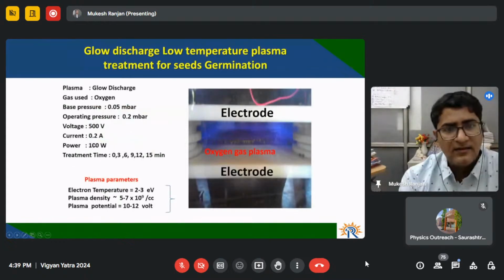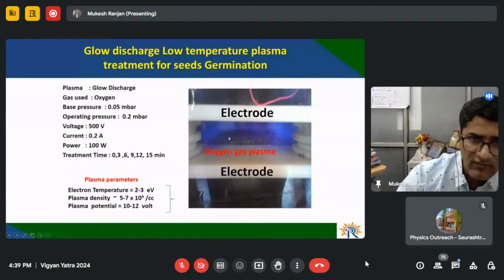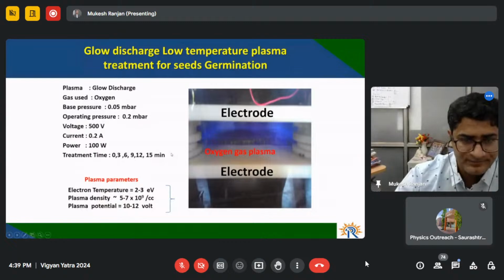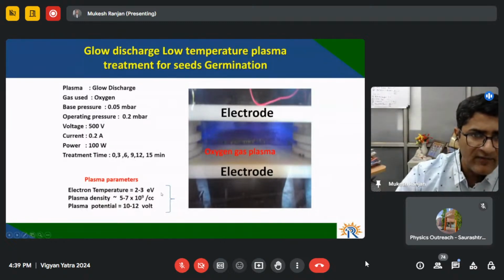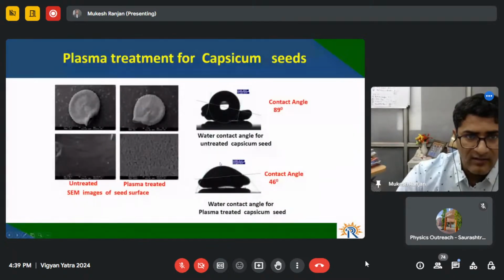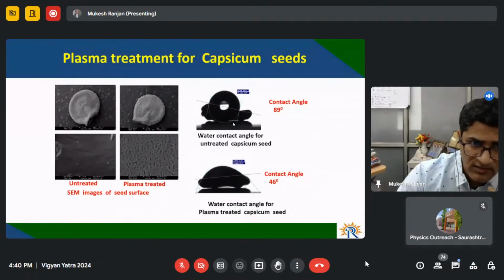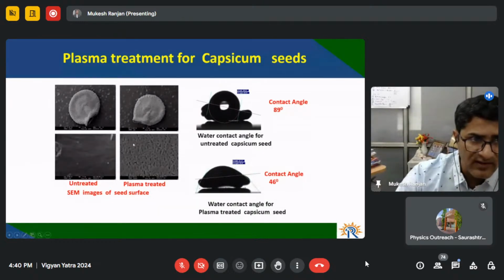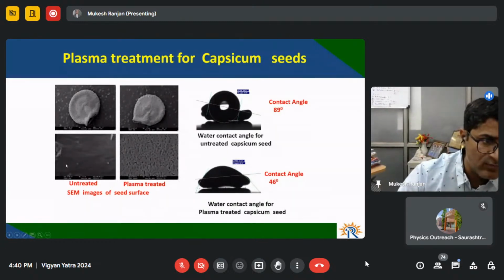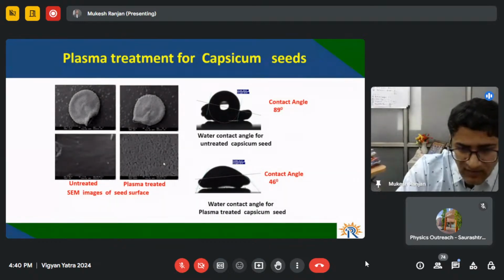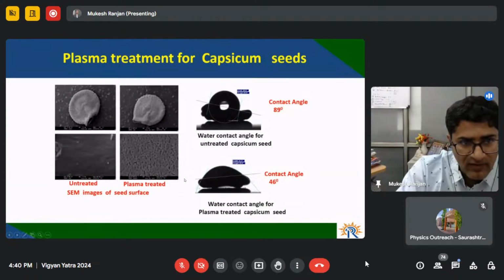Plasma, as I said, has applications in agriculture. If you have a seed, normally the seed takes some time for germination. There are reports available, and this is also our own work, where we have seen that when we treat some seeds with plasma, it removes the upper shell of the seed and makes its surface hydrophilic. So it absorbs much more water, and it grows faster. You can see the SEM images of the seed before and after treatment. The untreated seed is very smooth, and the plasma treated seed has some roughness generated on the surface. Once surface roughness is generated, the surface area increases, and it more easily absorbs water from different sides, and that's how the seed grows faster.